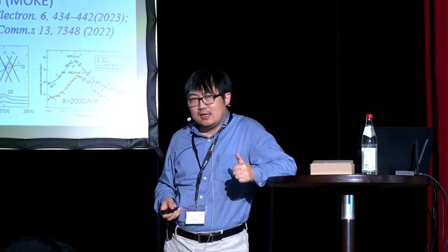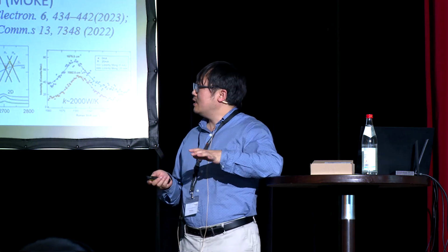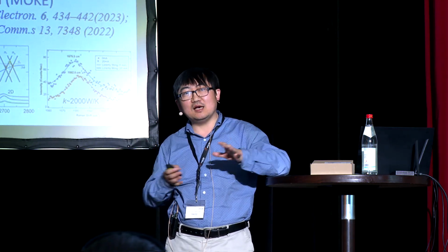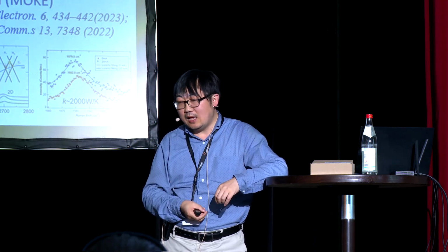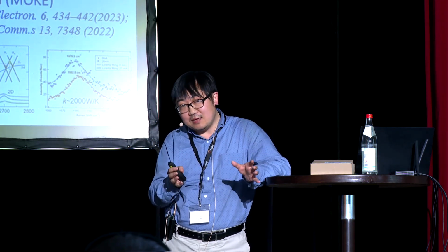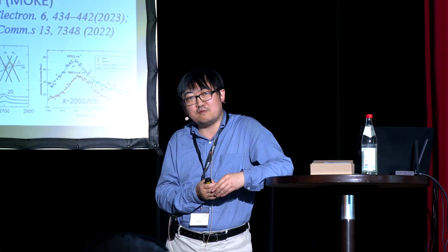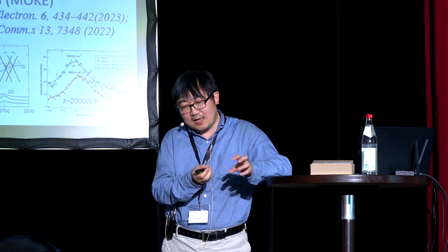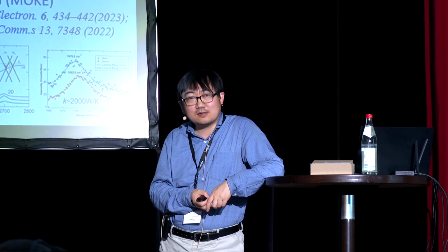Second question is about the structure. We've done some TEM images that show we form these moiré patterns with expected periodicity. We've also done some Raman imaging to show there's no obvious strain pattern. So I think those are the two pieces of information I can point out. But of course, more local probes to see detailed structures is still interesting.